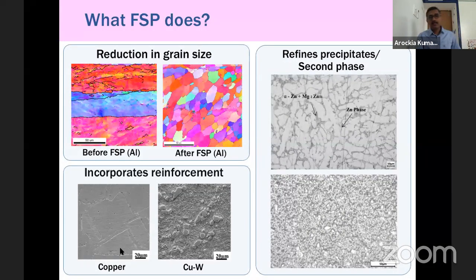And by means of FSP, you will be able to incorporate some particles. That means you will be able to produce a composite. So we have taken pure copper, and then we have distributed tungsten particles into pure copper. That way we have produced a copper tungsten composite. And here, we have refined the microstructure of a zinc magnesium alloy. What you are seeing here on the right hand side top is the microstructure of a zinc magnesium alloy. It's a two-phase alloy, a mixture of zinc plus magnesium zinc intermetallic.